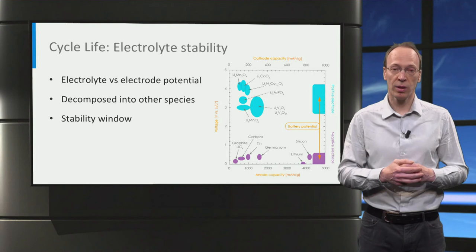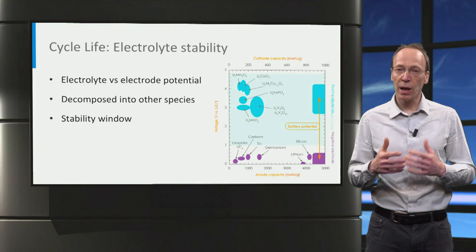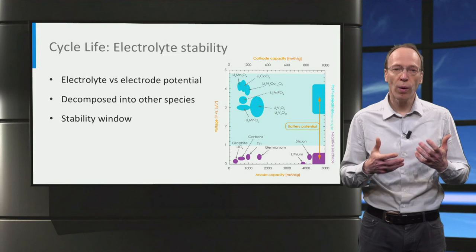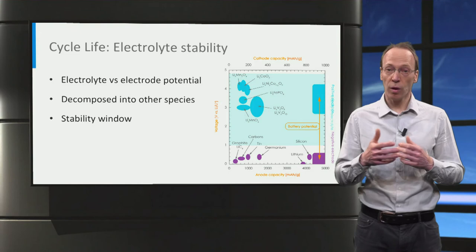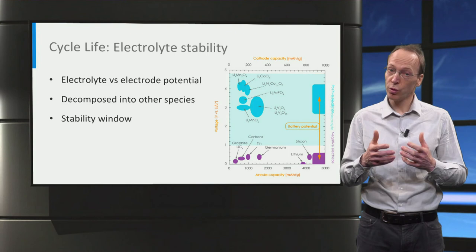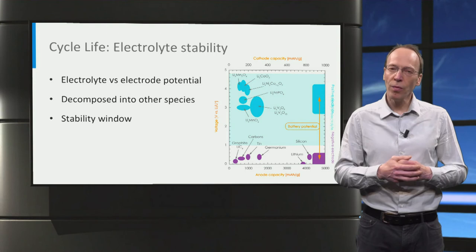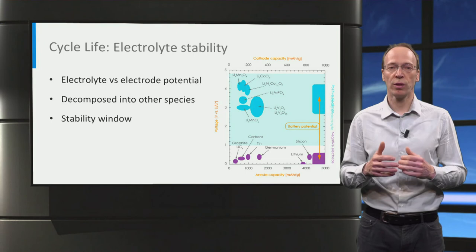For the large voltage of lithium-ion batteries, stable organic electrolytes have been developed. By mapping the electrolyte stability window on the potentials of the electrodes, we can determine which electrodes fall within the stability window. However, it is not always necessary to have electrode potentials within this window to achieve a long cycle life. Looking at graphite, the potential is below that of existing electrolytes, so the graphite negative electrode will reduce the electrolyte. Nevertheless, graphite is the most applied negative electrode in lithium-ion batteries. Depending on the electrolyte, its reduction leads to a solid electrolyte decomposition product on top of the graphite surface. This film is known as the solid electrolyte interface, the SEI.